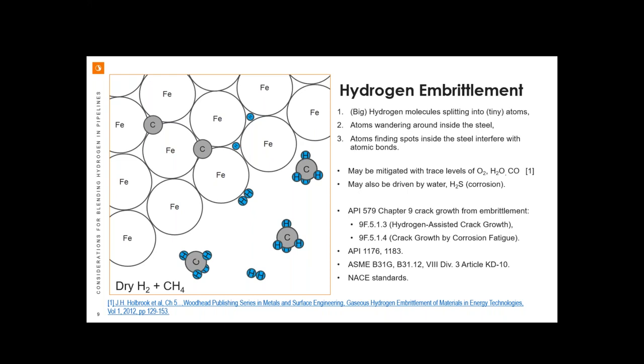So while diatomic hydrogen can split apart and diffuse through the steel, that's not the case with methane. And as far as the other molecules we would see in a typical gas pipeline, some can make things better or worse. Most famously would be the oxygen level, which is a whole different topic, but that can be a real game changer, it seems, as far as actually mitigating embrittlement. And we can definitely talk about that offline. Things like water could be good or bad, depending on how you look at it. And again, that's something we expect to see a little bit in our gas streams.